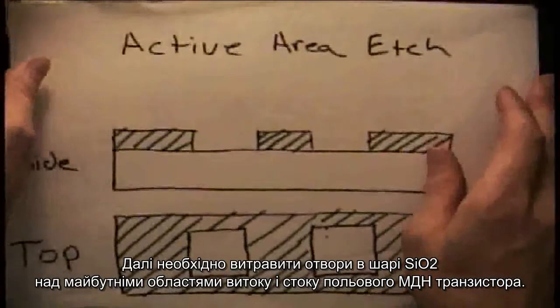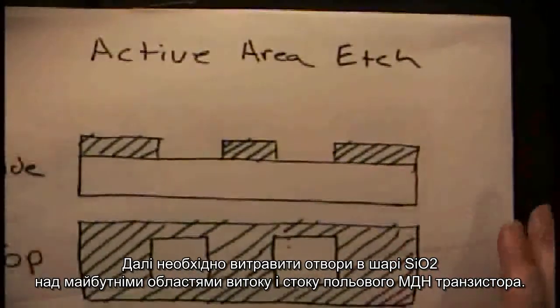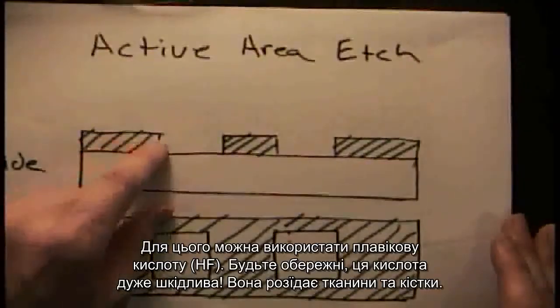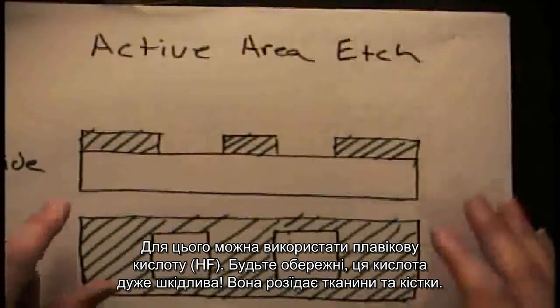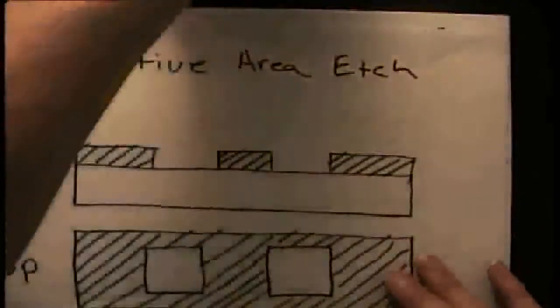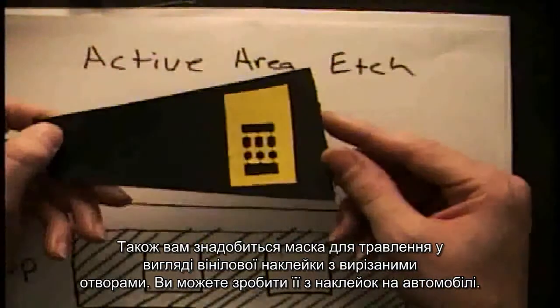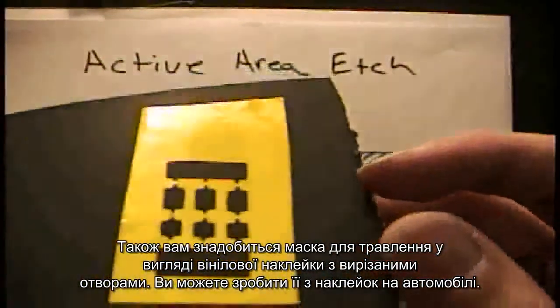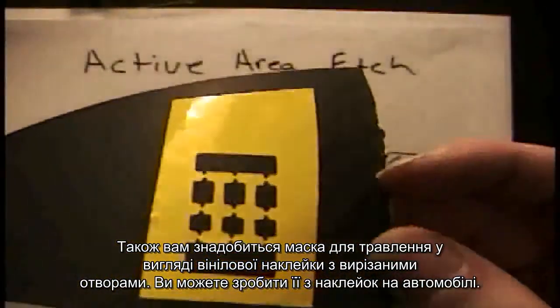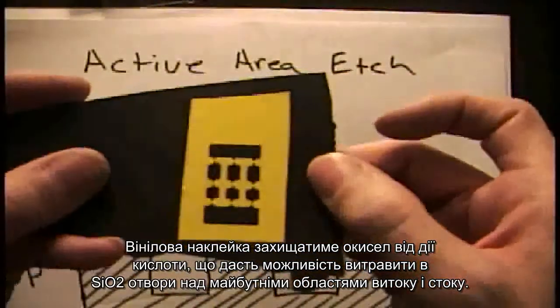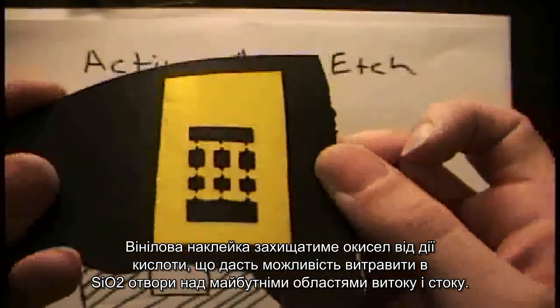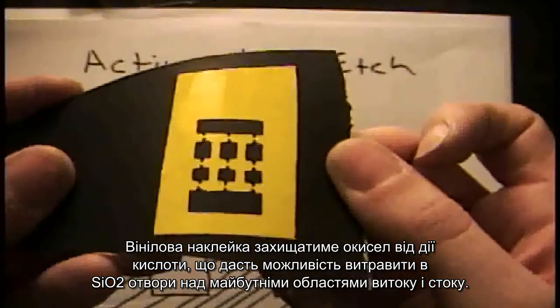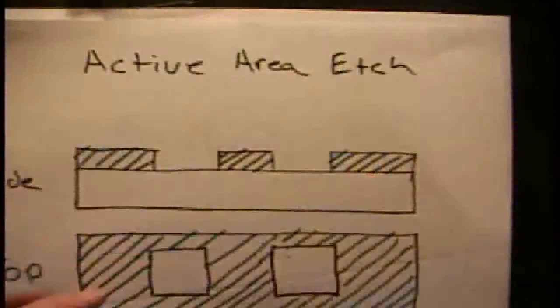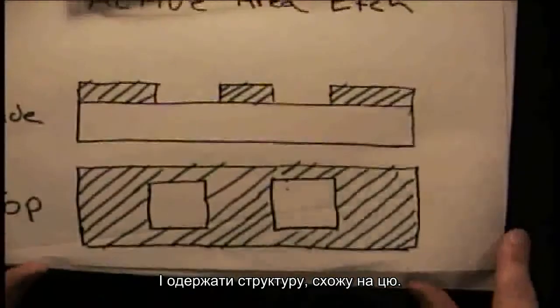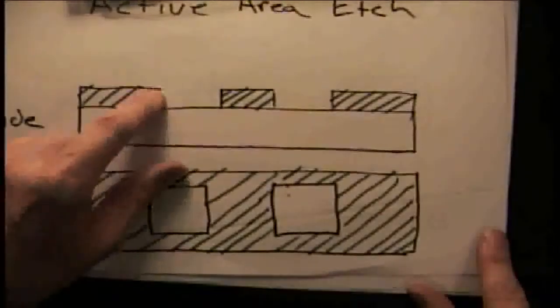The next thing you're going to do is etch the active layer. So you're going to use the hydrofluoric acid, and you're going to use a vinyl sticker mask that you can cut out. This is like the vinyl signs that you can put on the side of your car. So this is going to mask the oxide from the acid, and you're going to open up active areas into the wafer. You're going to make structures that look like this.